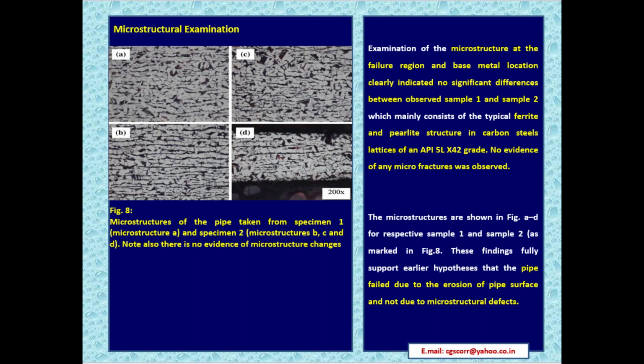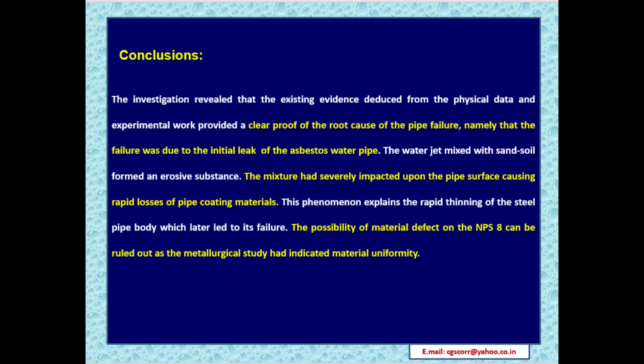The microstructures are shown in figure A to D for respective sample 1 and sample 2 as marked in figure 8. These findings fully support the earlier hypothesis that the pipe failed due to the erosion of pipe surface and not due to microstructural defects.